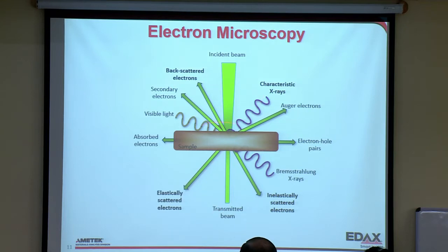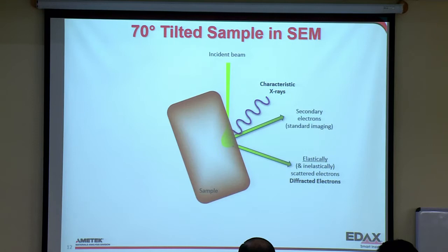If we go back to this picture, the TEM, you'll see here elastically and inelastically scattered electrons. So what happens to these when we go to SEM? Well, if we tilt the sample like this, we're in a mixed mode almost, because what we're doing is giving these electrons now a chance to escape, and we can detect them. Now I want you to think about, and this is the typical configuration for EBSD, we have an incident electron beam. But what we usually do is think of this as the source of the electrons. We think of an embedded source in the material. So you can kind of ignore the idea of this beam coming in.